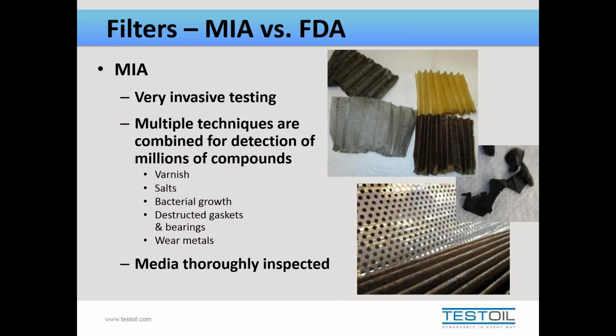So we mentioned a little earlier, but some of the abilities to detect are materials along the line of varnish that might be due to oxidation or thermal degradation or additive dropout, bacterial growth, or rubber that could indicate gaskets or seals have been compromised, damaged bearings, or an inorganic salt that could have been formed from the combination of oxidation byproducts and metal ions floating in the oil. And then also sometimes we see glycol contamination or even other strange types of materials such as fertilizer.